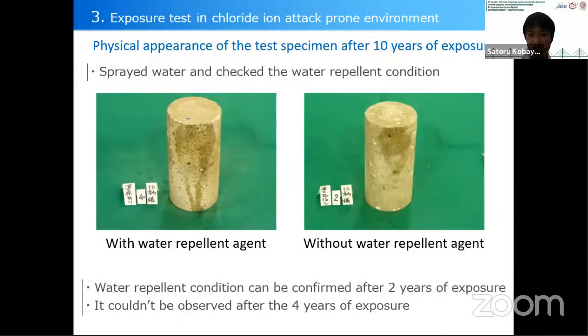This is the physical appearance after 10 years of exposure. I sprayed water and checked the water repellent condition. The right specimen is without water repellent agent. After spraying water, the specimen absorbed water immediately. The left one is with water repellent agent. After spraying, a little water drips from the surface, but the water can't be absorbed by the specimen. As a result, the water repellent condition can be confirmed until 2 years of exposure, and it could not be confirmed after 4 years of exposure like this.